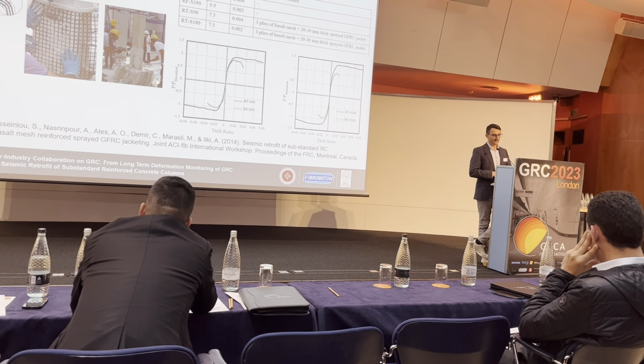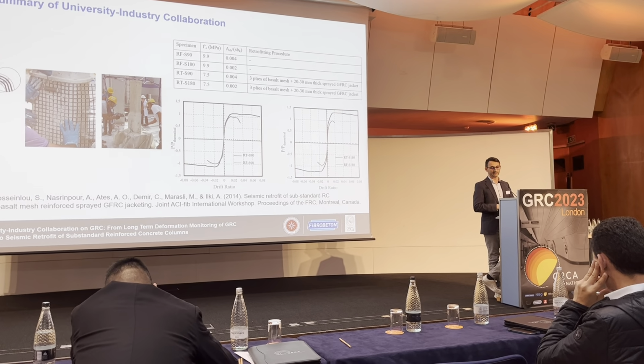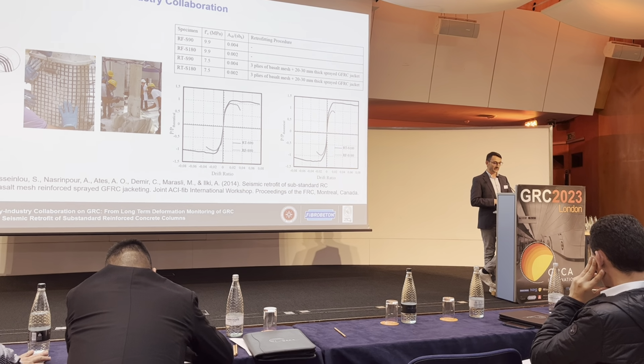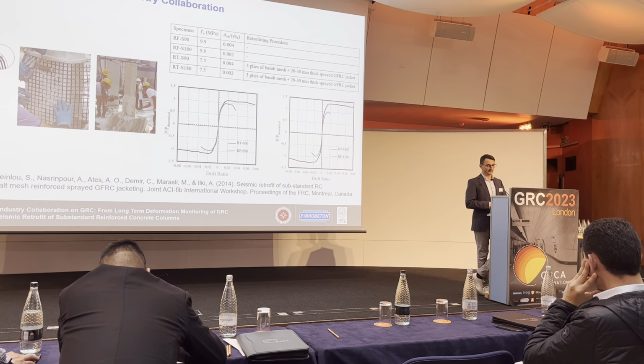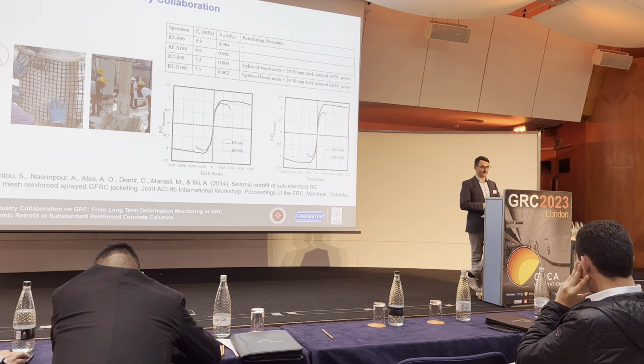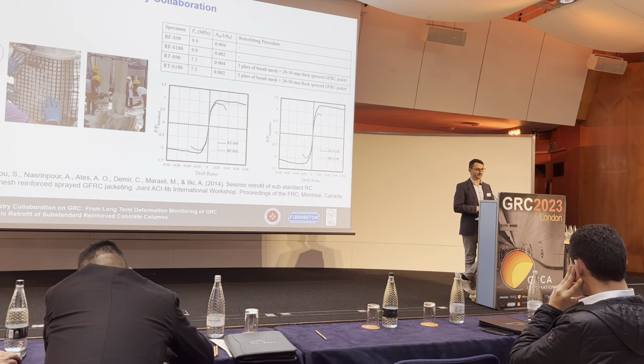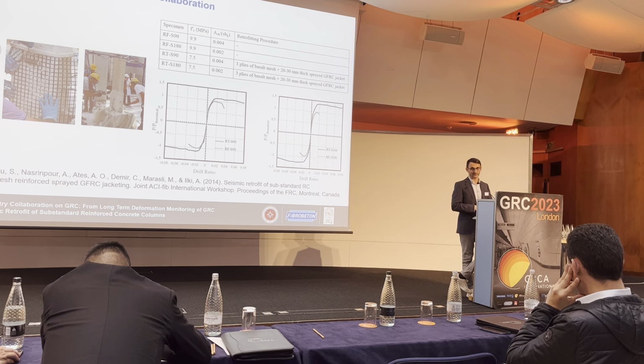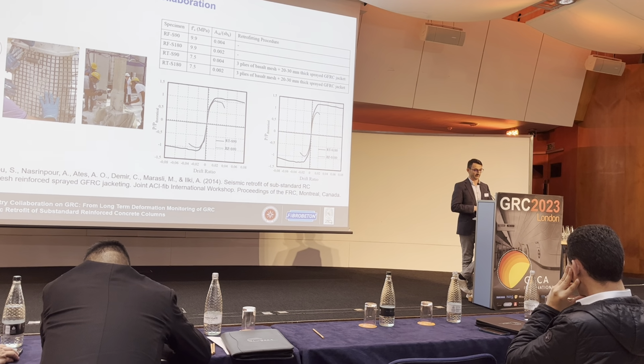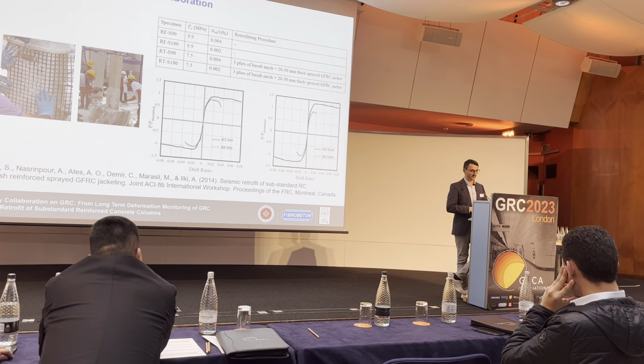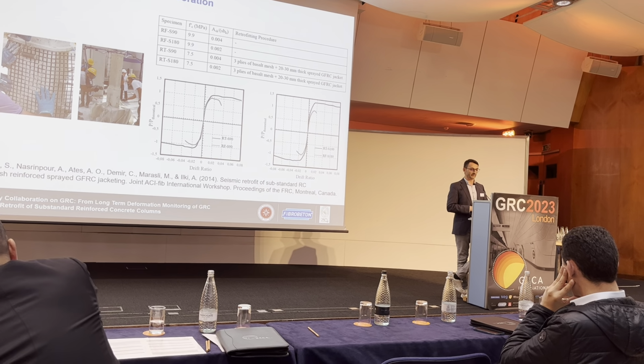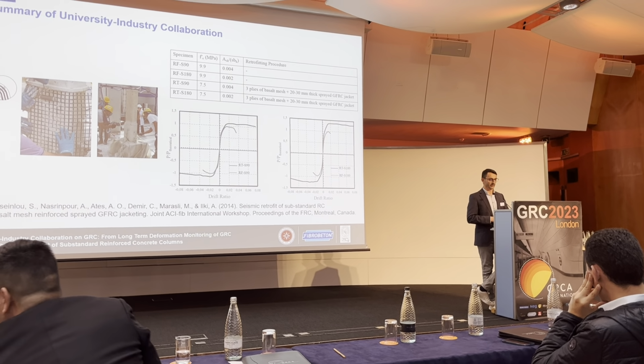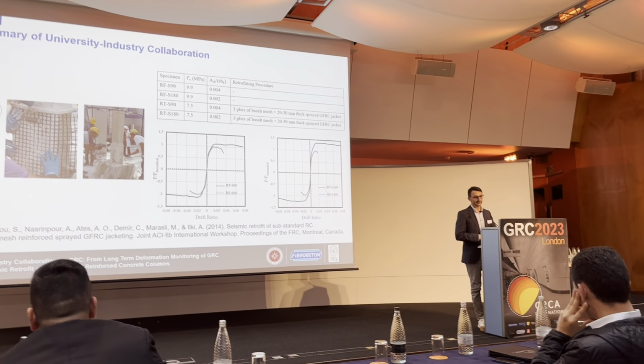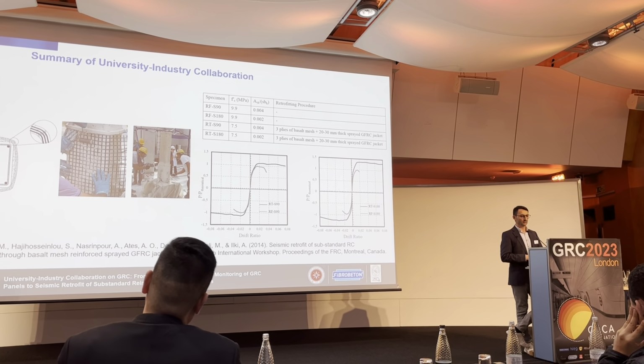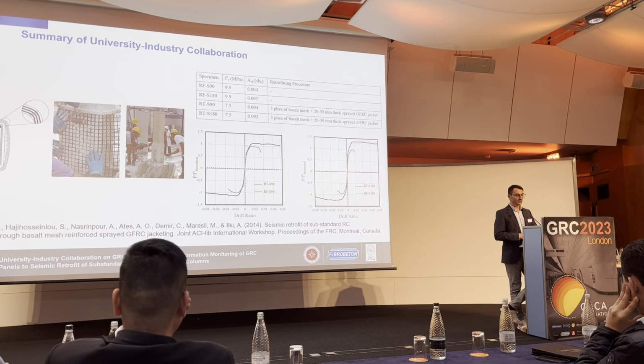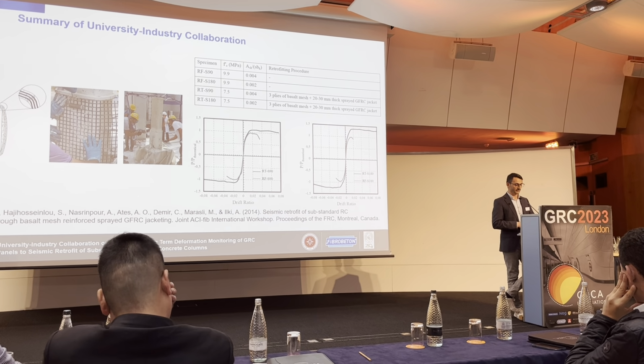So this study was a pilot study in order to understand if the method is working or not. We used it for the detailing of substandard columns, for example, with a compressive strength around 10 megapascals, which unfortunately is the average compressive strength in Turkey. So this represents the existing building stock. We have a lateral reinforcement ratio around 2 per thousand, and we applied 3 plies of basalt mesh reinforcement with 2-3 centimeters thick of spray GRC, with 2 different stirrup spacing configurations.